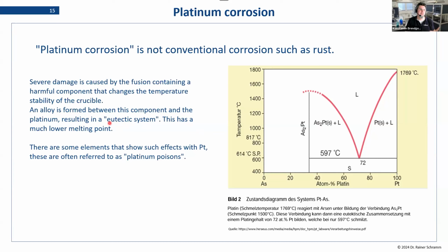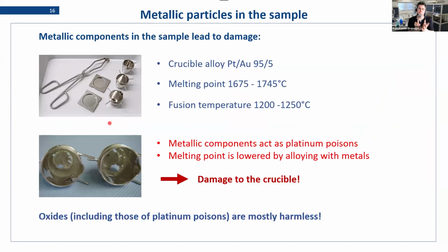But basically, we want to understand platinum corrosion usually means that there is an alloy forming and that can potentially damage our platinum vessel, our dish, or our casting mold. So let's have a look how that works in our field of work. When we have anything metallic in our sample, be it a ferroalloy or a contamination, this can cause this effect. So a general rule of doing samples is make sure they are not metallic, because depending on the alloy, the fusion temperature that we are operating our equipment at, which is around 1200 degrees, is enough for platinum to form alloys with a lot of elements.